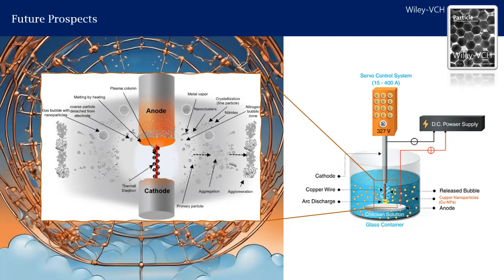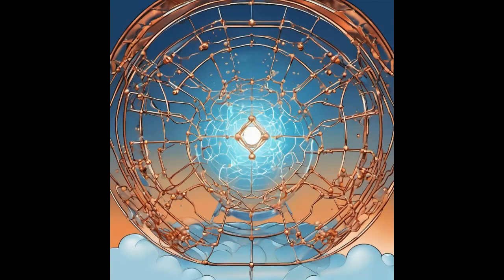Despite larger sizes, nano copper in double distilled water show faster reduction rates, completing in 32 minutes, while those with 0.10 Wt% chitosan take 72 minutes. These findings highlight the importance of stabilizer choice in nanoparticle synthesis and its impact on catalytic performance and kinetics.